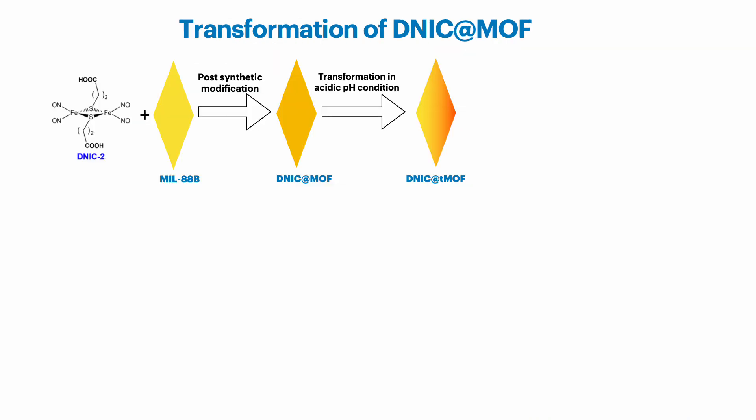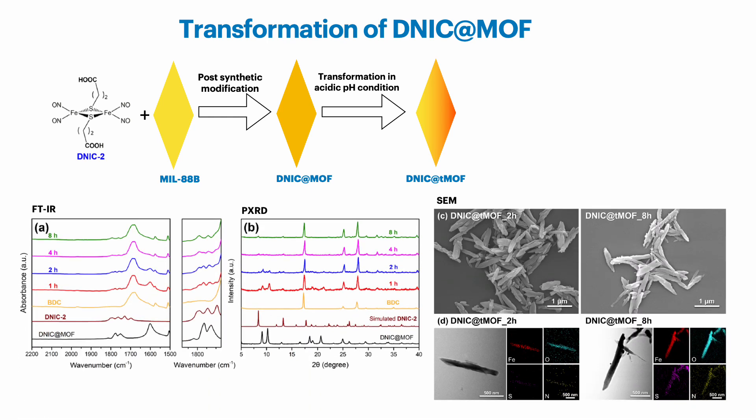Next, we utilized simulated gastric fluid for further stability testing in an acidic environment. After incubation of DNIC at MOF in simulated gastric fluid for 8 hours, we found intact but shrunken microrods. This transformation of the microrods was again confirmed with FTIR, SEM, and TEM.